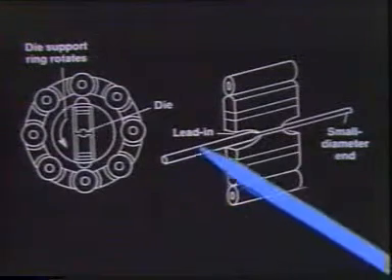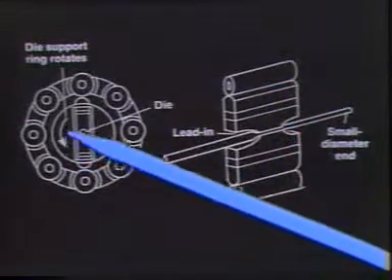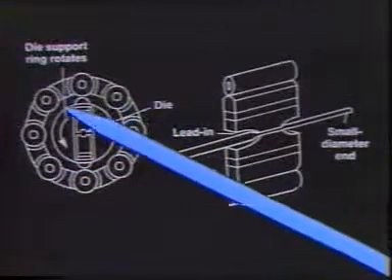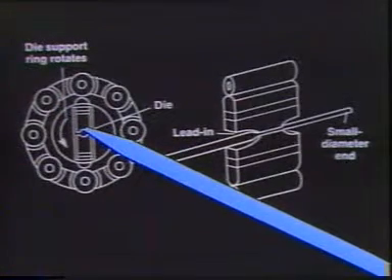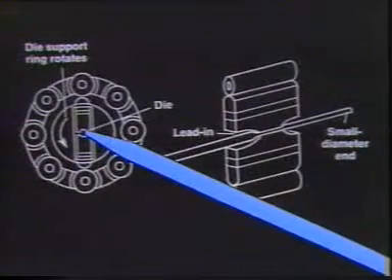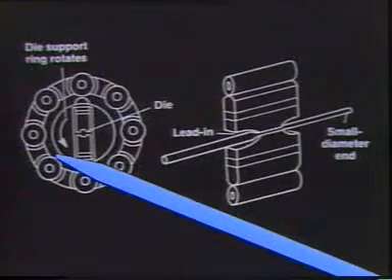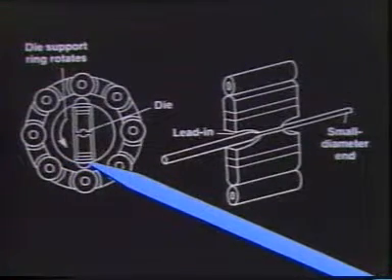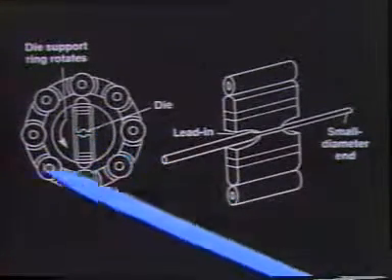In this particular case, the hammers, which are these two hammers situated inside of this ring, as it rotates and passes each one of these rollers, it forces the little hammer down to bang on the material. So the material is advanced axially through that cylindrical array, and as it's advanced, this thing rotates rapidly, and it just hammers it from every side and keeps on making it smaller and smaller. So it's a way to make a round rod without pulling it through a die, right? And actually you can do appreciably more reduction in area at one pass this way than you could in wire drawing.